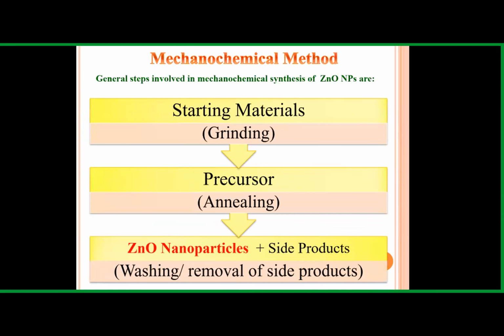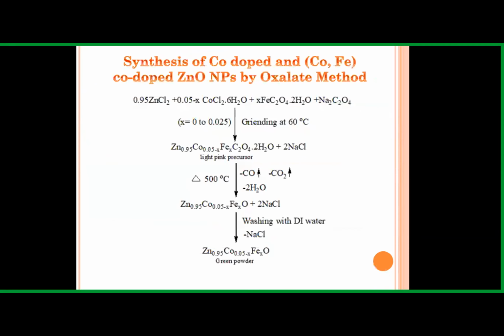Both these strategies were carried out by the mechanochemical method, in which we ground the starting materials, and the precursor obtained was annealed at temperatures from 300 to 400, 450 degrees. The zinc oxide nanoparticles were prepared along with side products, which were washed away by a simple method. So these are the synthetic strategies that we have used.